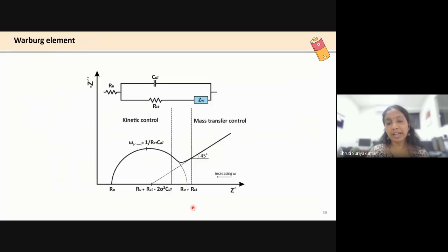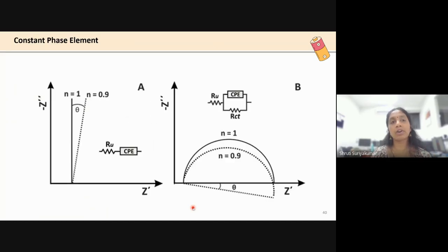So again, when most of us are doing our experiments, I heard that many of you have done your experiments, we are not going to get such beautiful semicircles. We will have semicircles that are suppressed. Some you would feel look like a mountain kind of profile. You're going to get different profiles. So one main parameter, just like the Warburg element, is another parameter, and that is called the constant phase element. A constant phase element is something that is not an ideal capacitor, because an ideal capacitor has a very clean surface and the roughness is not going to be there, but in a real system you'll have electrode roughness, you'll have porosity associated with it, all those factors come into the picture.